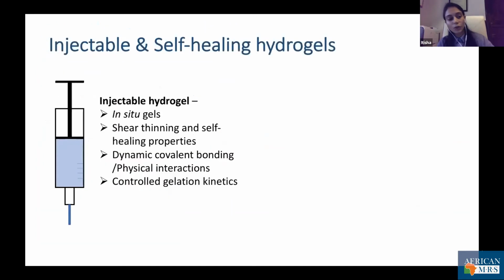So this brings us to another type of hydrogels, which are injectable and self-healing hydrogels. One of the properties of injectable hydrogels can be in situ gels, so that the gel precursor is injected at the wound site and it cross-links under physiological condition. Now, the injectability of these gel precursors or the hydrogel itself depends on their shear thinning and self-healing properties, so that the bond breaks during injection and reforms after injection, which necessitates dynamic covalent bonding, that is, physical interactions. Now, one common example is Schiff base reactions, which are reversible.